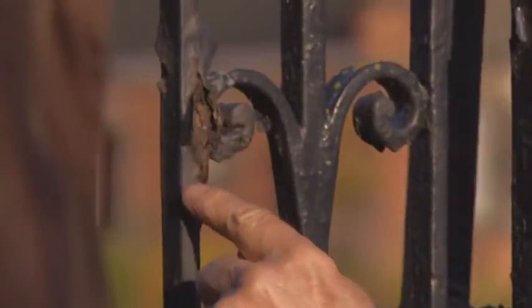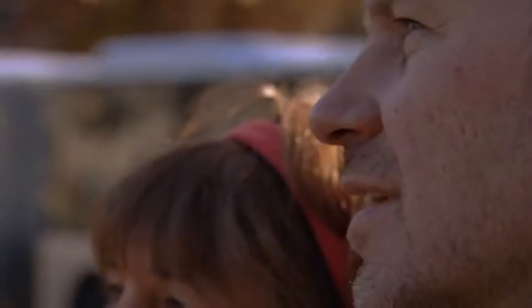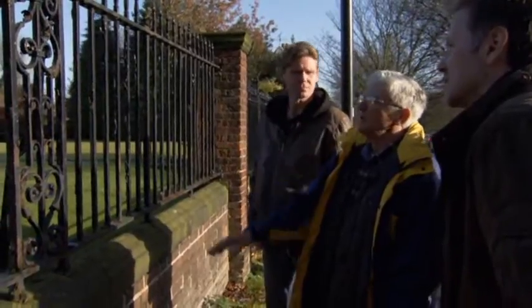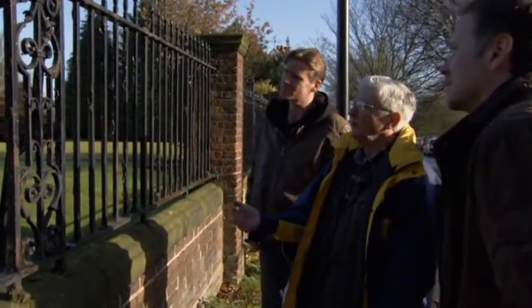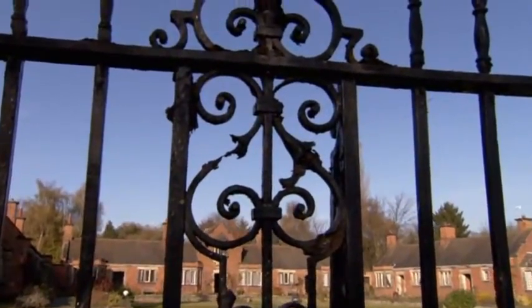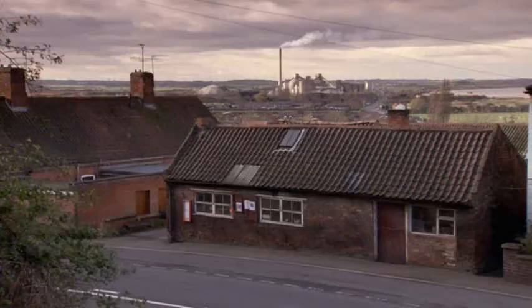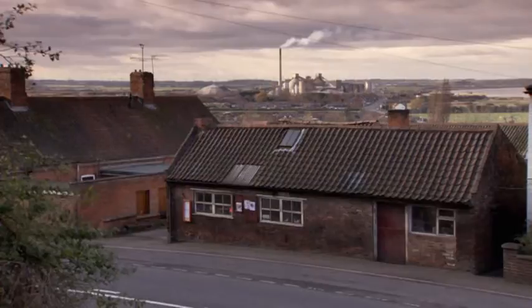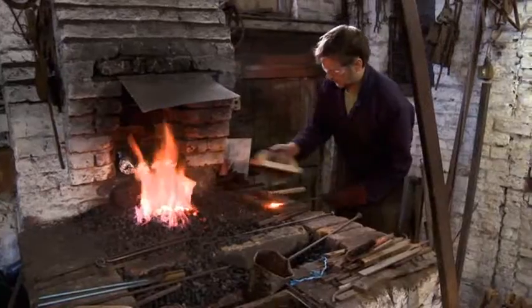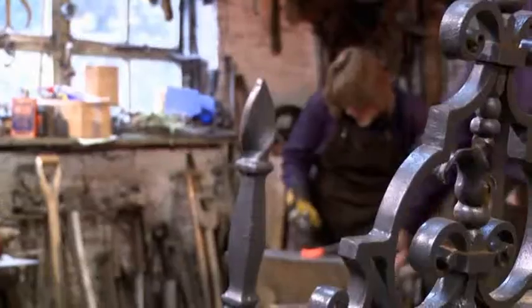These are the John Burrell Almshouses in York, one of Don's current restoration projects. This is badly manufactured material — it's only been here since about 1930, which is ridiculous when you think it should have lasted hundreds of years. Some railings produced before 1945 were made from inferior quality wrought iron and are very susceptible to rust and erosion. You can see areas where delamination is taking place — it explodes, basically. The trainees are given three days to make replacement components; if they're good enough, they'll be included in the restored panel.